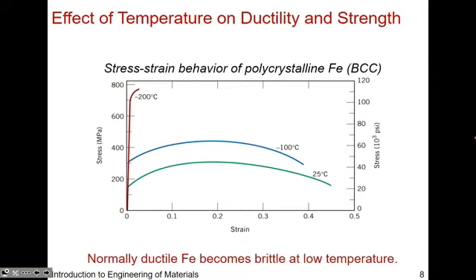So we've already seen from the YouTube video what happens to metal when you drop the temperature, right? As you mentioned, it goes through brittle fracture. So you can see here the stress strain curve at room temperature, 25 C. You can see it's quite ductile, right? So if we look at the permanent strain at fracture, if this is the slope, voila, that is your ductility. And then you can see that ductility decreases at negative 100 C. And then basically you have elastic behavior and then just fracture. Okay, it's going to be quite brittle. What you've also noticed is the slope here doesn't change. So the modulus, the stiffness, doesn't change. You've just changed the ductility and the toughness of the material, but you haven't changed its stiffness at all. Okay.